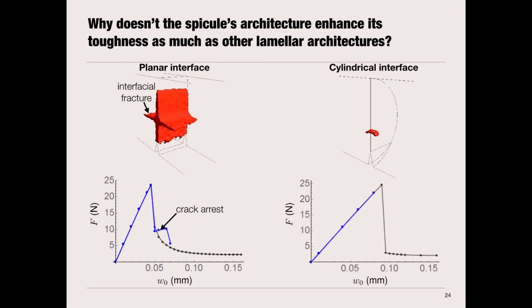If we look at the same thing for the cylindrical interface, what's very interesting is that we don't have that same jump in the force displacement curve. We still see the crack deflection at the interface, but we do not see crack arrest occurring. We attribute this to the geometry of that interface. That's work that's still being explored in the Kesari lab, from a computational and a theoretical standpoint, looking at the role of interface curvature on both promoting or suppressing toughening mechanisms like the Cook-Gordon mechanism.